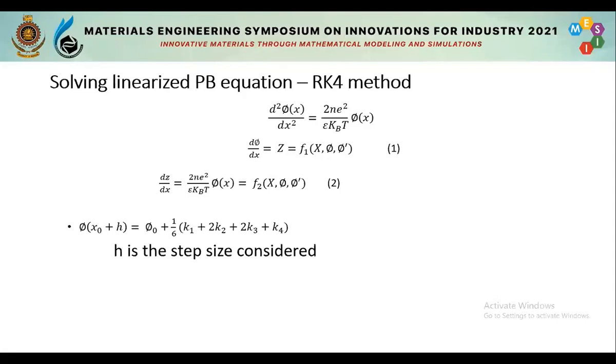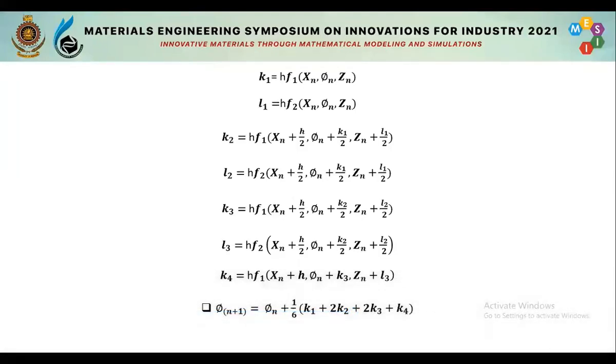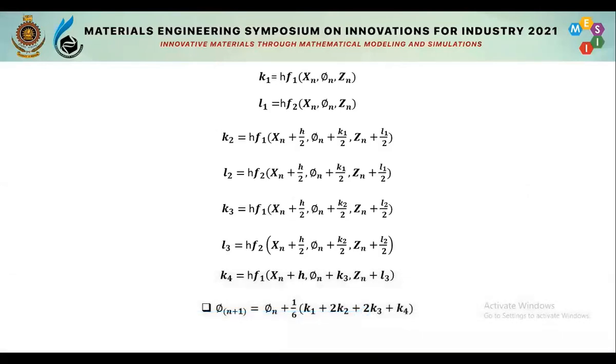Here, the range which we are considering in our case is the distance from the electrode surface to the point of consideration, and it is divided into a number of steps, of which the step size is h. Further we reduce h, we can get more accurate results. These calculations are repeated a number of times when calculating the potential of a single point. So when determining the potential distribution, we have to calculate the potential of huge numbers of points within the double layer depending on the step size h we select.